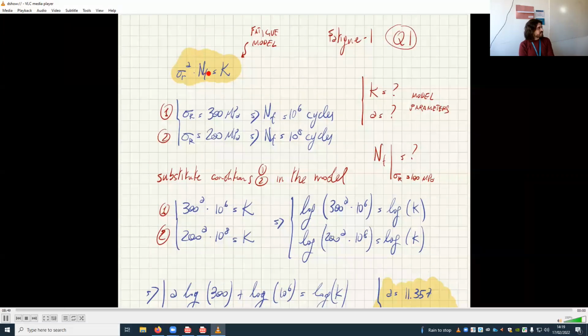So this is just an experiment. Remember Wöhler's curve, Wöhler's experiment. Just say, okay, let's see how many cycles it takes until it breaks. So you just fit a curve. That's what you're doing. So if you use megapascal and cycles, that's fine. You get some numbers here that will work with megapascals and cycles. So as long as you are consistent every time, you always use megapascals, you always use cycles, you will be 100% fine. If you start mixing and matching units, you might be in trouble.